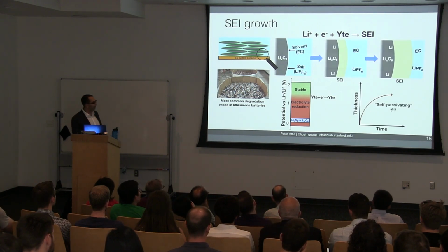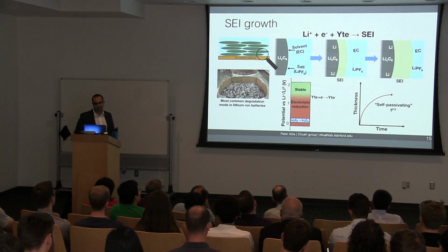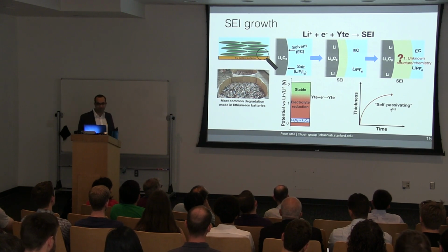Now, if we measure battery degradation during storage, we actually find that it also roughly corresponds to self-passivating growth. The capacity fade scales with t to the 1/2. But we still have some key questions about how this actually works. The first is the composition of the SEI. We really don't know what the SEI structure or composition is on the nanometer scale.